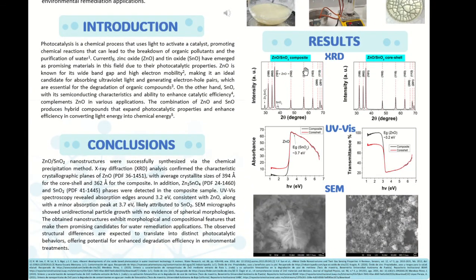Conclusions. Zinc oxide with tin oxide nanostructures were successfully synthesized via the chemical precipitation method. X-ray diffraction analysis confirmed the characteristic crystallographic planes of zinc oxide with PDF 36-1451, with average crystallite sizes of 394 angstroms for the core shell and 362 angstroms for the composite. In addition, zinc stannate PDF 24-1460 and tin oxide PDF 41-1445 phases were detected in the composite sample.